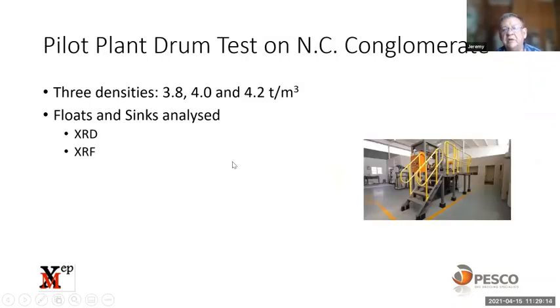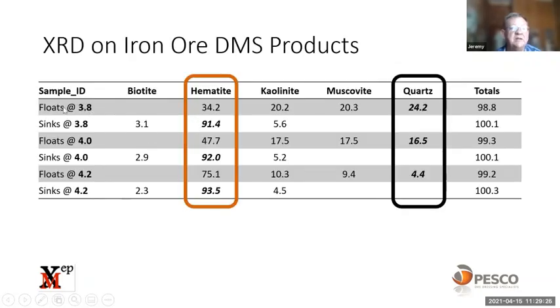Here are some examples of pilot plant drum test work on a Northern Cape conglomerate. Three densities were tested, and the floats and sinks were analyzed using XRD and XRF. So there are the floats and the sinks for the 3 densities. If we look at the hematite, we can see as the cut density increased, the amount of hematite in the sinks increased, and the amount of quartz in the floats went down.